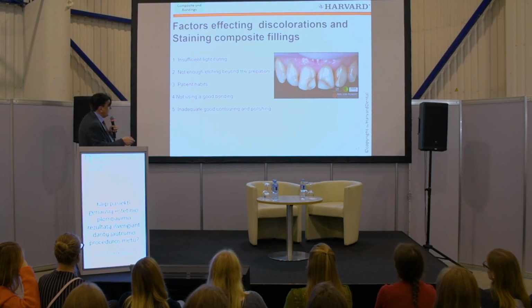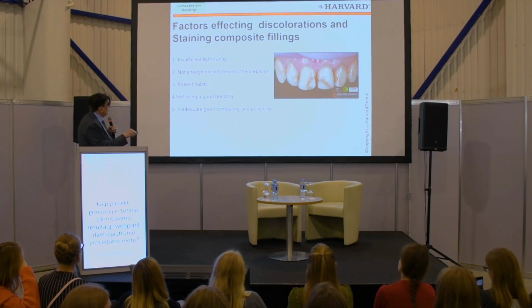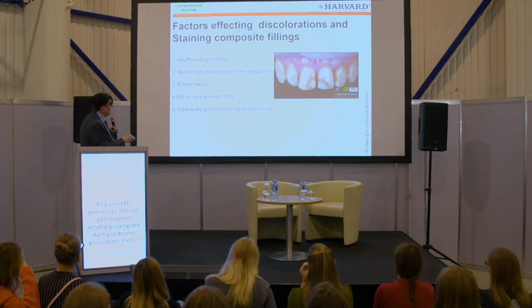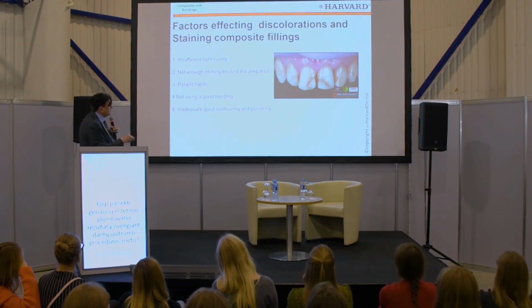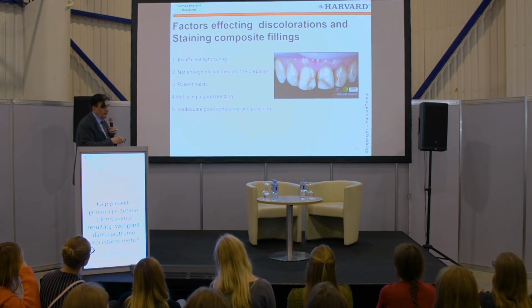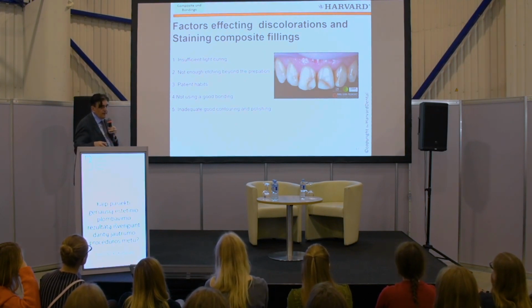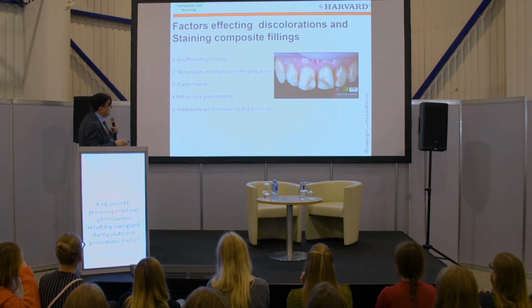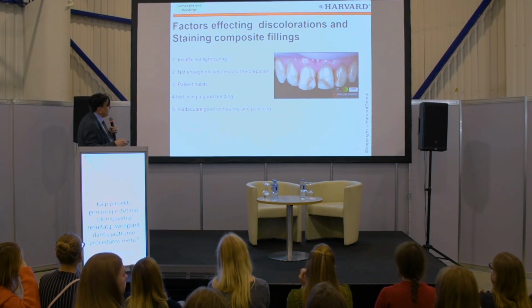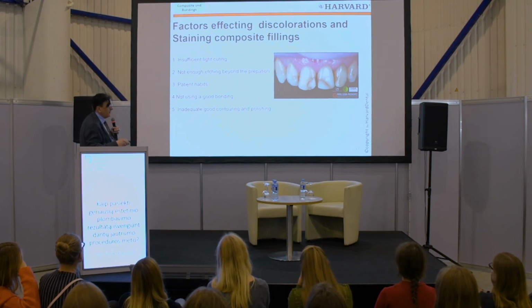This is what we spoke about. Why do you have this? It could be a bad habit, that the patient smokes, or insufficient light curing. The light cure doesn't penetrate all the way inside. Or not using a good bonding, or you didn't obey the instructions on how to use the bonding with the total etch. I like with this case to use the total etch and primer and bonding. Total etch for enamel and dentine, then apply the primer, then apply the bonding.